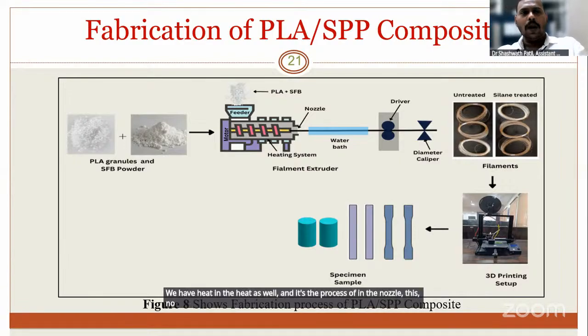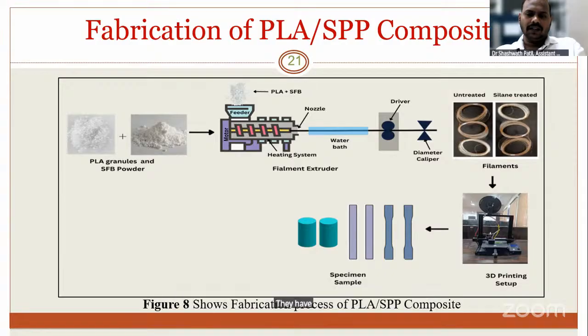At a temperature of around 180 degrees, we have heated it in the heated zone, and the material goes through the nozzle. This nozzle has a 1.75 mm diameter. It is the standard diameter for printing material, as the market-ready size is 1.75. That is how we extracted this composite material. Then immediately we passed it through the water bath, and using this Vernier caliper, we measured whether the fabricated filament has the 1.75 diameter, and then we wound it with a spool.